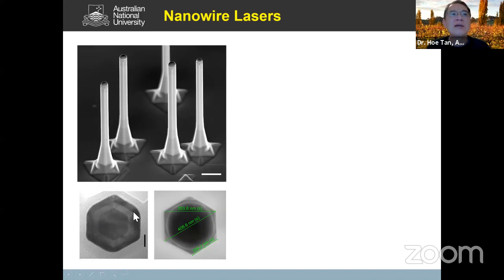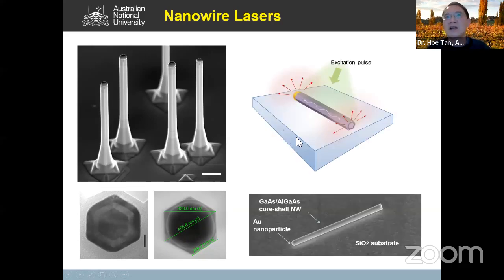And after that, we protect the aluminum gallium arsenide with another thin layer of gallium arsenide. The reason for that is aluminum gallium arsenide oxidizes very easily in air, okay? So if you don't protect it, it will oxidize. After we've done that, you can see the diameter of the nanowire is effectively 400 nanometers. Then we knock it down on a quartz substrate, excite it with a pulse laser, and measure the output from this nanowire.